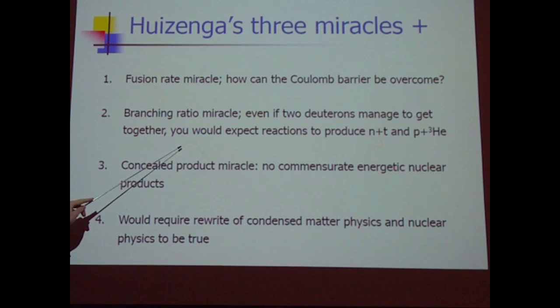And then for number 2? For number 2, if you have an incoherent fusion reaction, then 2 plus 2 goes to 3 plus 1, 50-50 roughly. And Huizenga's saying, okay, you don't see 50-50, show me how in an incoherent reaction you deviate from 50-50, knowing full well that the answer is there's no way you can do that at all. That's hopeless. And my answer is, let's not try to change the 2 plus 2 going to 3 plus 1 branching ratio for the incoherent reaction.